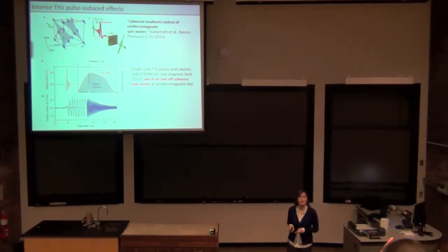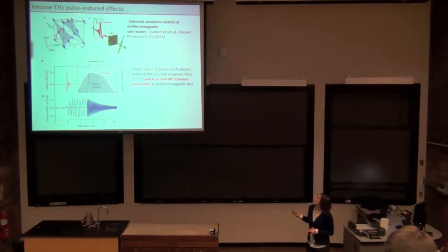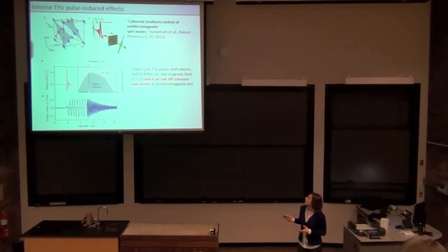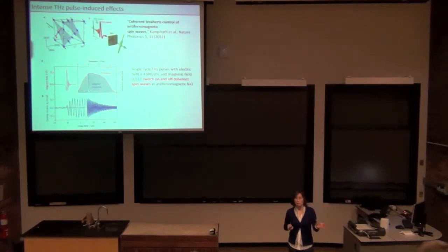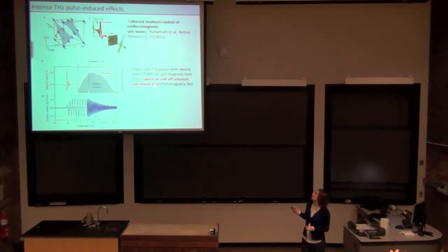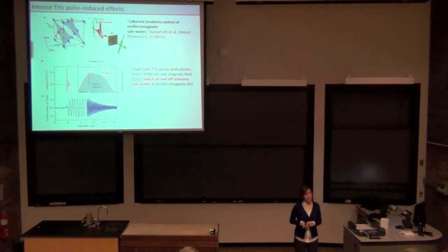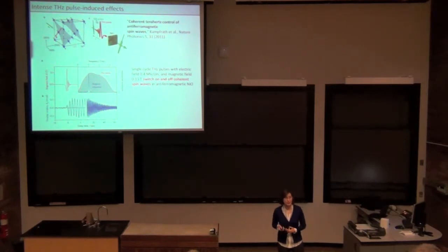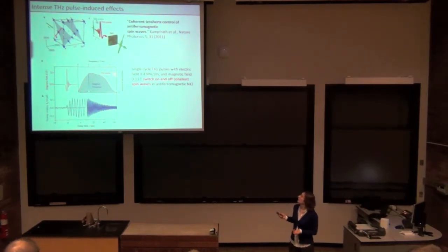This is very recent, just published in 2011, by a German group. When we're talking about optical pulses or terahertz pulses, we're usually ignoring the magnetic field because it's low. But when you get to electric fields, which in this case they have 0.4 megavolt per centimeter, you can no longer ignore the magnetic field because it becomes 0.13 tesla. That's now considerable. So they looked at nickel oxide, an antiferromagnetic material which is known to have a spin wave or magnon mode right at 1 terahertz.